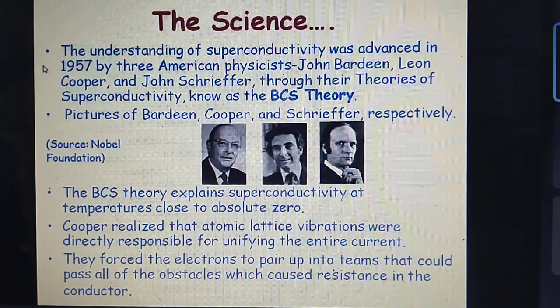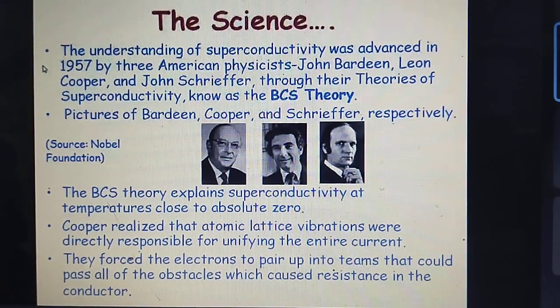Cooper realized that atomic lattice vibrations were directly responsible for unifying the entire current. They forced the electrons to pair up into teams that could pass all the obstacles which caused resistance in the conductor. And they also said this will specifically happen at low temperature. One should remember that at low temperature, there is a pair of electrons, which we call a super pair. They get bound together because of a virtual phonon. Because the lattice is vibrating, a quantized lattice vibration is what we call a phonon. Because of that virtual phonon, those super pairs get entangled and they move in the lattice without any resistance. Mind it.